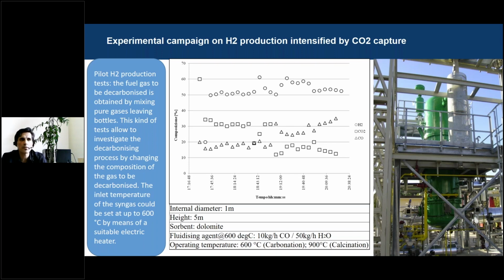And as you can see, this is a very explorative experimental campaign, but nevertheless we were able to attain good results, because the gas leaving the carbonator has a hydrogen content oscillating between 50 and 60% on a dry basis. The remainder is composed of unreacted CO and CO2, which we were not able to capture because the calcium oxide would convert it into calcium carbonate. This means that we have to add more calcium oxide in order to lower the content of CO2.